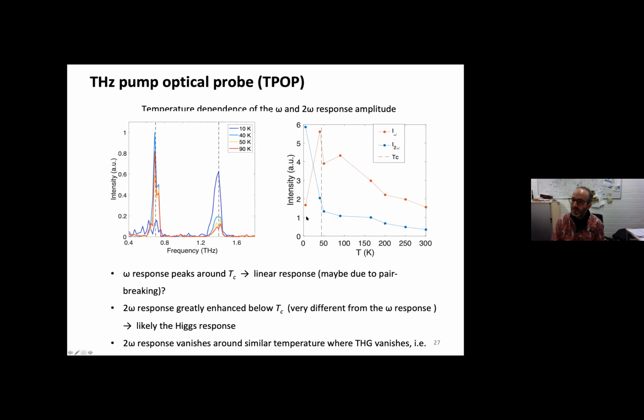would expect for any current in a superconducting response. However, our 2 omega responses really become heavily enhanced below TC, which shows they are not due to screened currents, but are really due to driven Higgs oscillations in the system that set in below TC in this material. The question is now, of course, why are there 2 omega responses even above TC in this system?